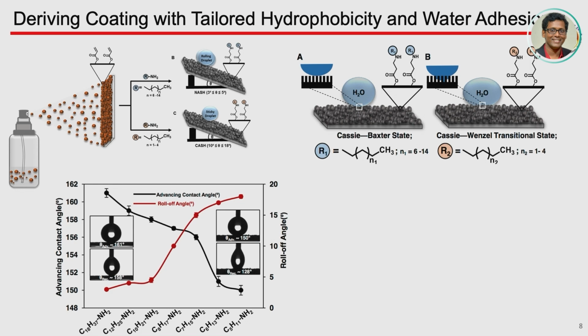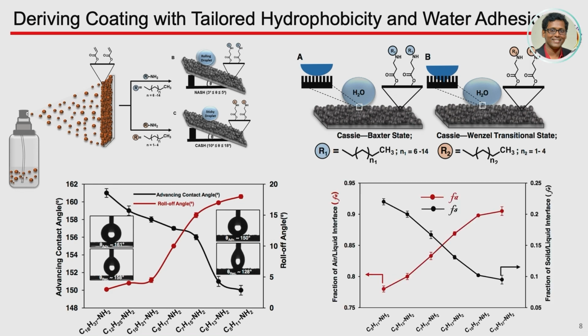Now, how it is happening is basically how you attain the Cassie-Baxter model, which is responsible for non-adhesive superhydrophobicity, and the Cassie-Wenzel transitional state. Basically, how you are modulating or managing the trapped air in this porous coating, and that is precisely maintained through this chemical modification. As you can see, the fraction of contact area of the beaded liquid on the solid surface varies regularly depending on the change in hydrocarbon tail length. But the only problem with this particular design is that we cannot really modulate the wettability and the adhesion property orthogonally. It's a single chemical modification giving two different properties, right?